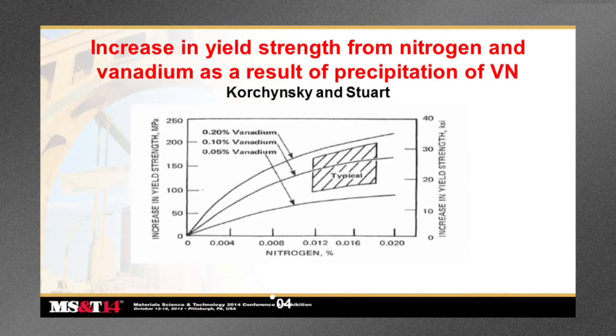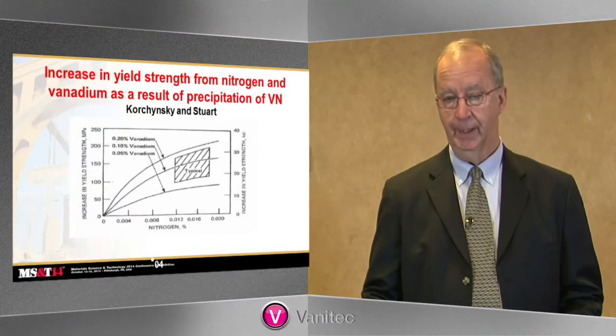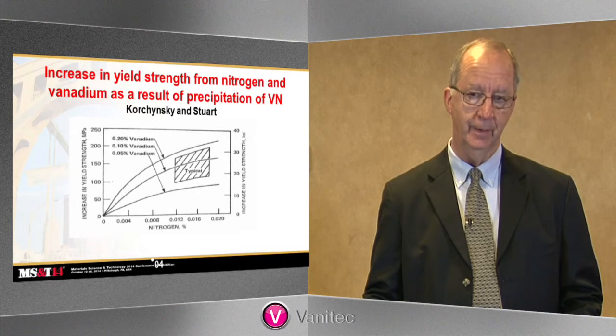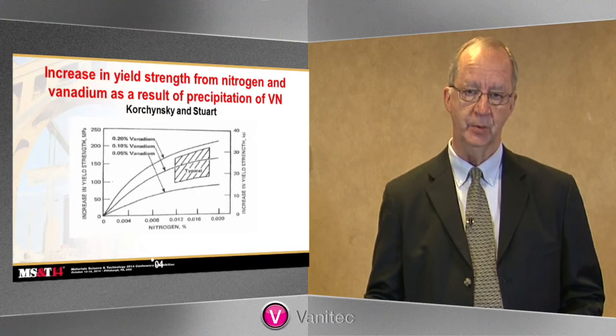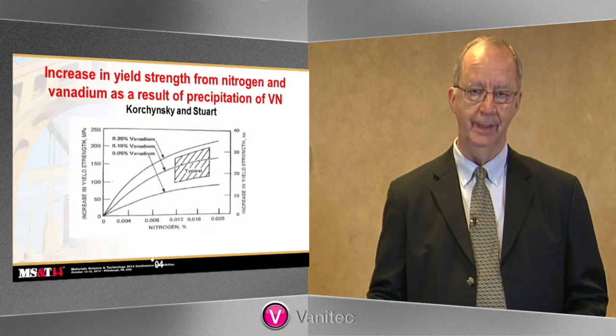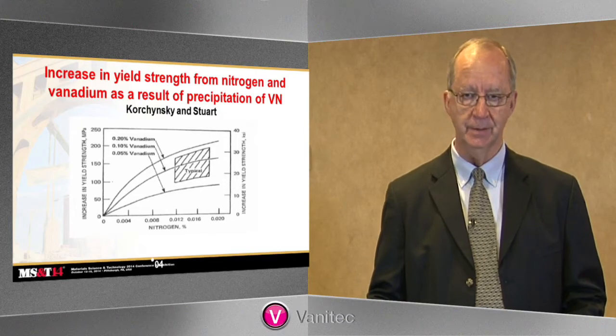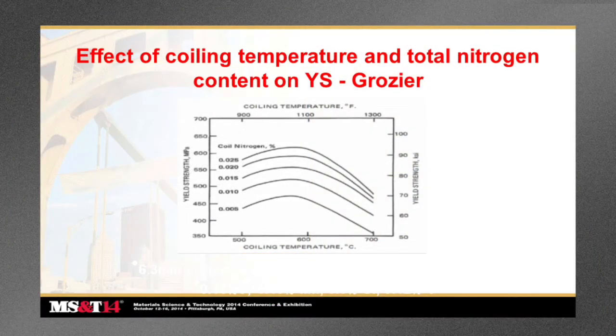This is the graph first published again by Korchynsky and Stuart, showing the strengthening effect, that is the increase in yield strength as you see on the left, for various nitrogen levels, for increasing nitrogen levels for 3 different levels of vanadium addition. This again is quoted widely, cited widely over the years as being the first real representation and information to the industry that the vanadium nitrogen system could be very effective. This is the effective coiling temperature graph that was also included, and again shows the relative effects of nitrogen levels on vanadium bearing steels. Again, widely used.